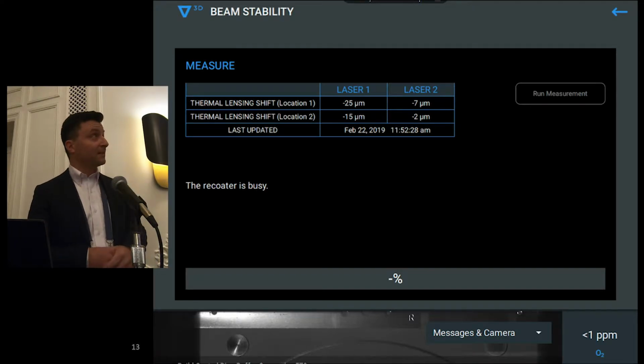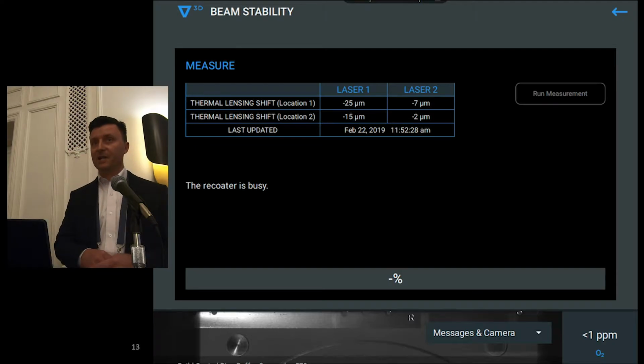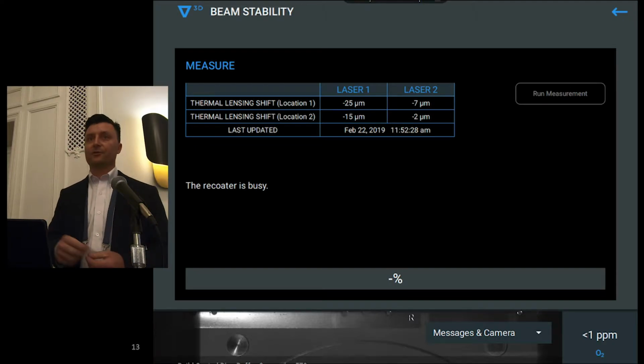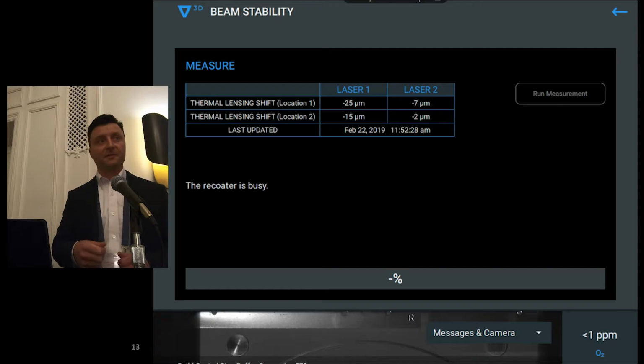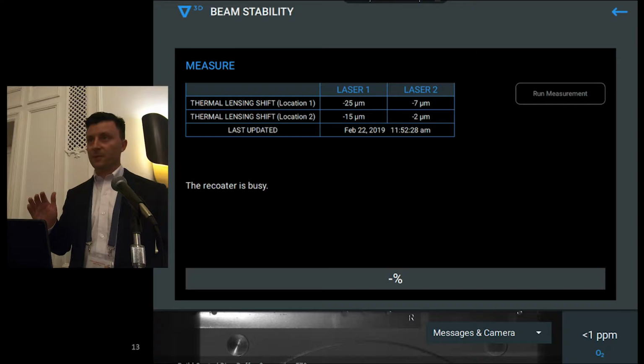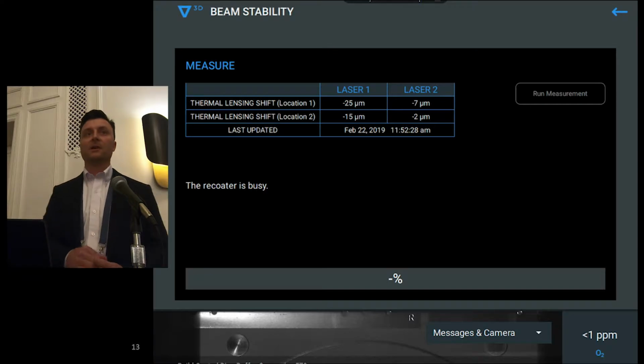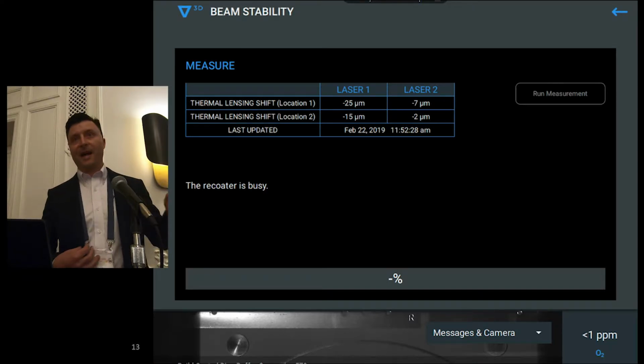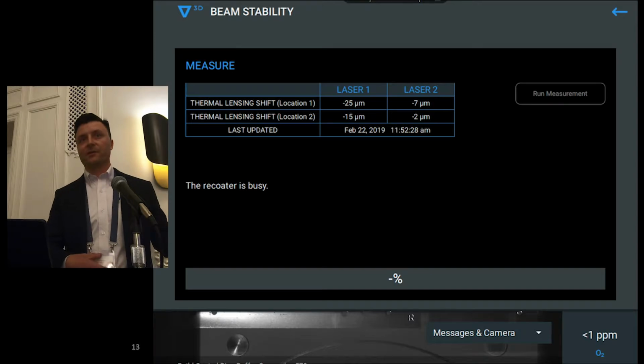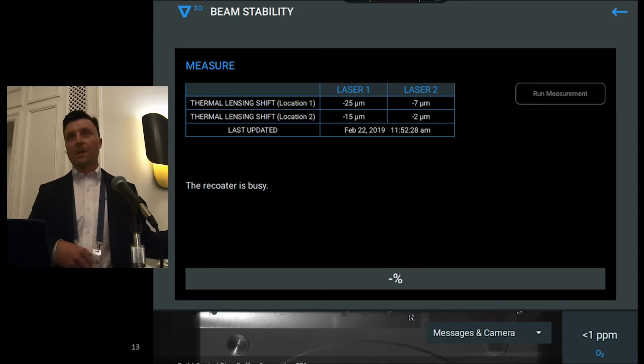So we've built into the system the ability for it to actually measure the spot size and to attribute that to causes. And one of them is thermal lensing. So we can measure the thermal lensing live during the build, again, at any point during the build. This is not actionable by the machine because if your window's dirty, the machine's not going to clean its own window. But this is something that we find changes over long time scales.